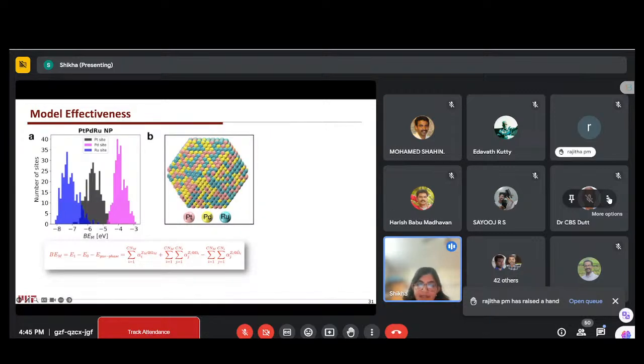So suppose I create a big nanoparticle having more than 3000 atoms, and I want to calculate the binding energy of each element on the surface. What I will do is just run my script by giving the structure of the nanoparticle, and immediately I can see the result: the range of the binding energy spectra I have for ruthenium, for platinum, and for palladium.